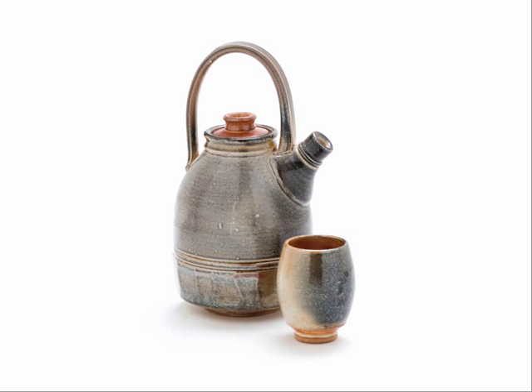Here's an old teapot and cup, and this is a shino glaze, a carbon trap shino. In these early years, I used a gas kiln to finish my work. Gas fired to — in pottery speak — cone 10 gas reduction, meaning fired to about 2350 degrees in terms of temperature, and reducing the oxygen in the kiln. This particular glaze gets a smoky look because it actually traps excess carbon, and that's where the blacks come from.